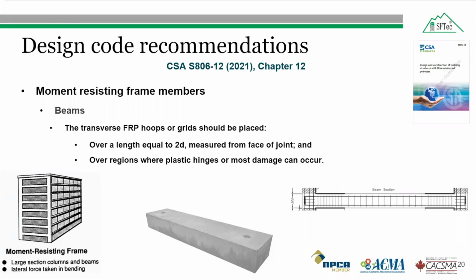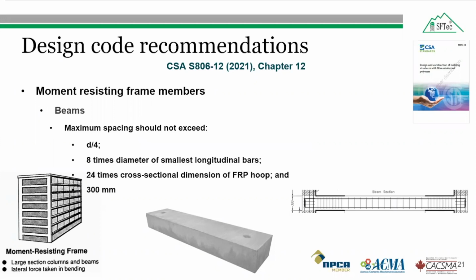And the transverse fiber reinforced polymer hoops or grids should be placed over a length equal to 2 times D, where D is the effective depth of the beam measured from the face of the connection, and over regions where the plastic hinges are, or where most damage in the case of the fiber reinforced polymer bar beam could occur, and should be reinforced for a distance equal to the beam effective depth on either side of this hinge region. The first fiber reinforced polymer hoop should be located not more than 50 millimeter from the face